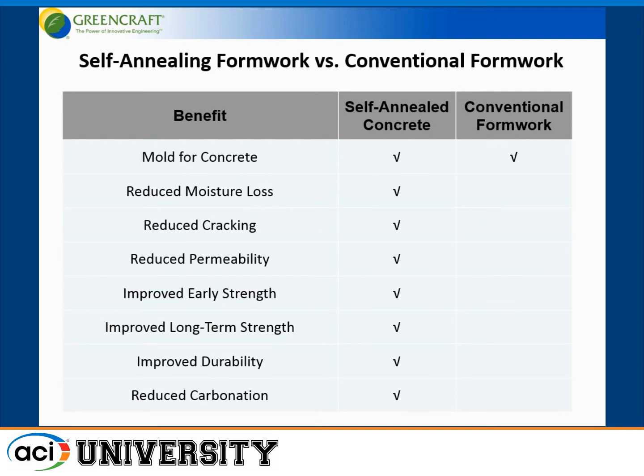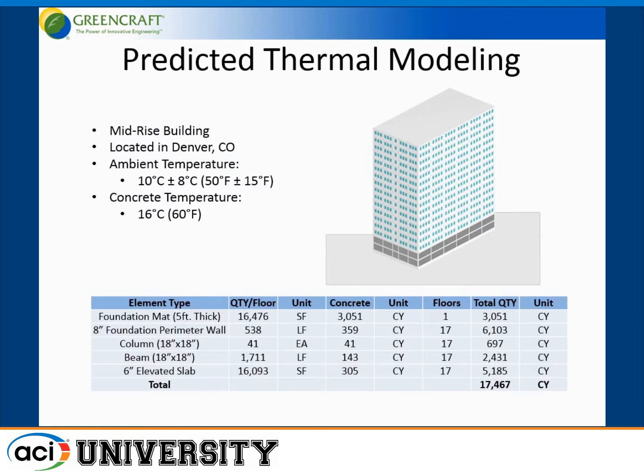The self-annealing formwork versus conventional formwork, I don't want to talk down on the formwork folks. They have tremendous improvements over the engineering of the systems, over productivity and so on, but at the end of the day, it's still only a mold for concrete. And I believe that formwork can be a whole lot more than just a mold for concrete. You can improve properties of concrete through it. Through the self-annealed formwork, we can reduce the moisture loss, reduce cracking, reduce permeability, improve the early strength, improve long-term strength, improve durability, reduce carbonation.